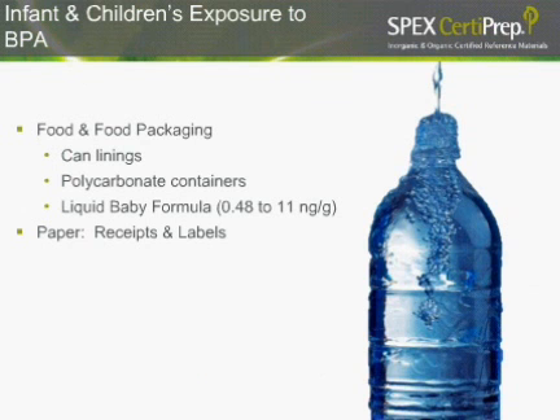A surprising route of bisphenol A exposure is paper labels and receipts. These are mostly the thermal transfer receipts, and not all thermal transfer receipts, but a good portion of them. These receipts use a process that has a coating of free bisphenol A on the surface of the receipts. And by handling these receipts, the free bisphenol A can get on the hands, the face, and in the mouth.